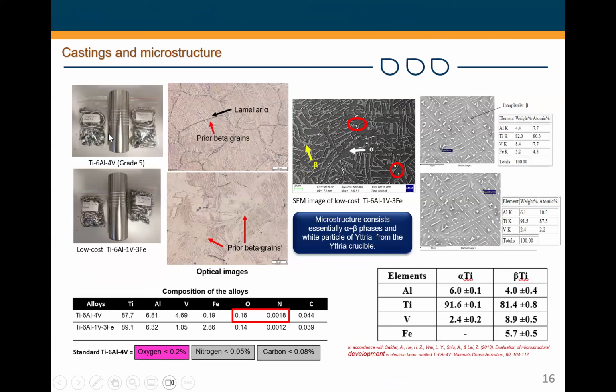This is the Ti64 we produced, the commercial grade, and of course we were able to produce our experimental alloys as well. And you can see just looking at both, after machining, you can really see the difference between the two of them. But of course, if you analyze the composition, you would see the difference. And of course, we tried to look at the microstructure of the Ti64 and that of all of the experimental titanium alloys. But I'm showing the microstructure of this particular one where we retain 1 weight% of vanadium, and we replace the rest with 3 weight% of iron.